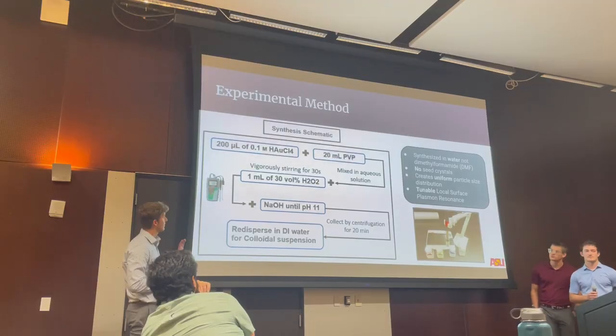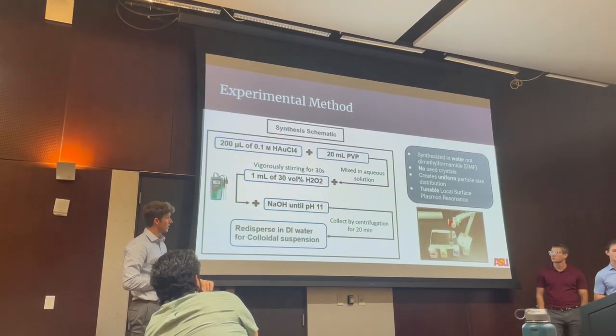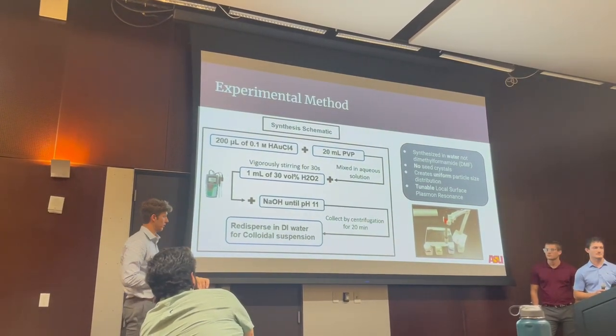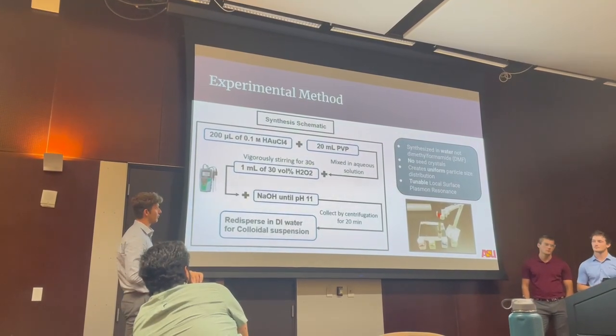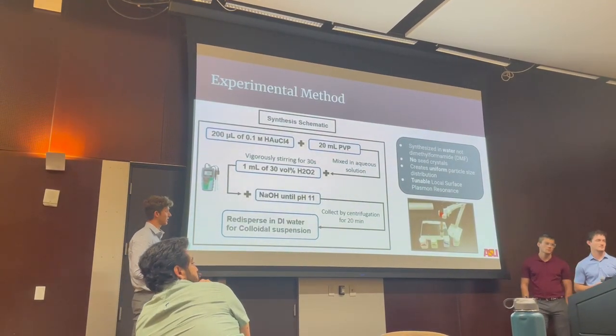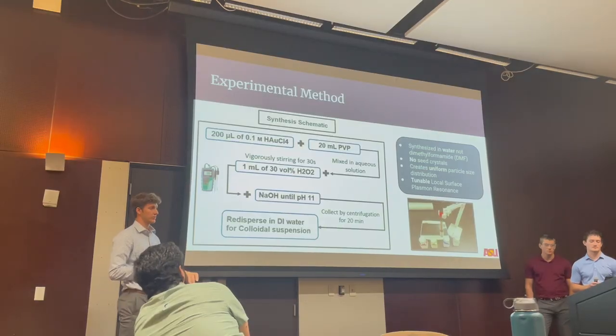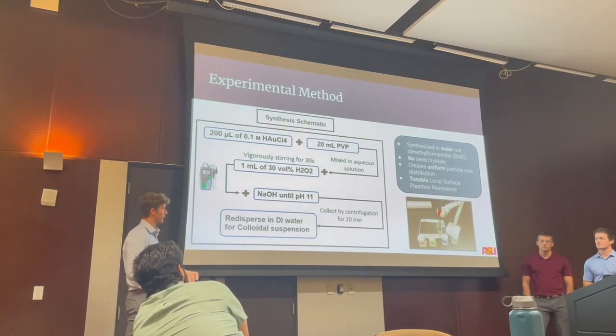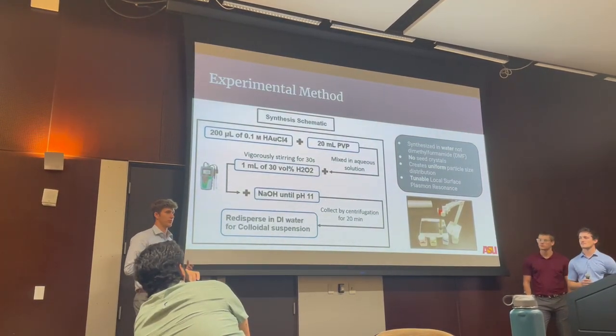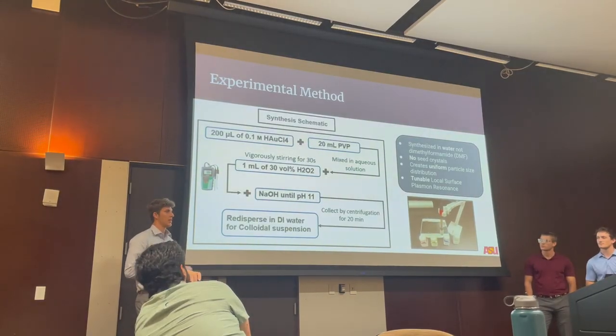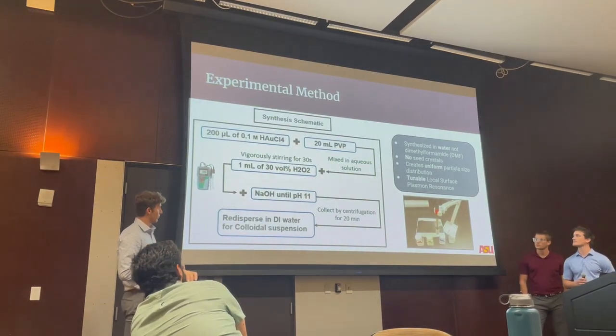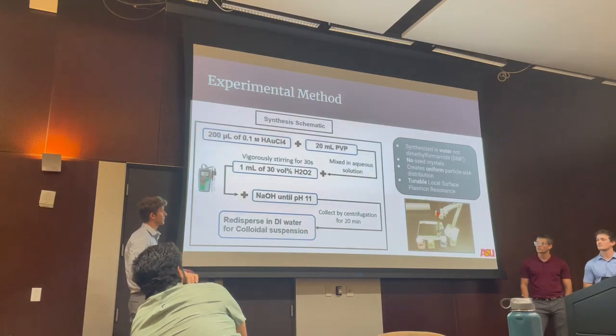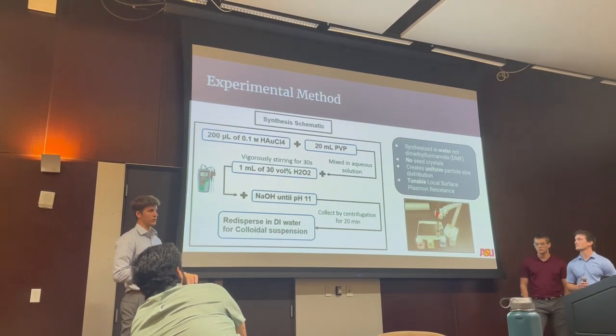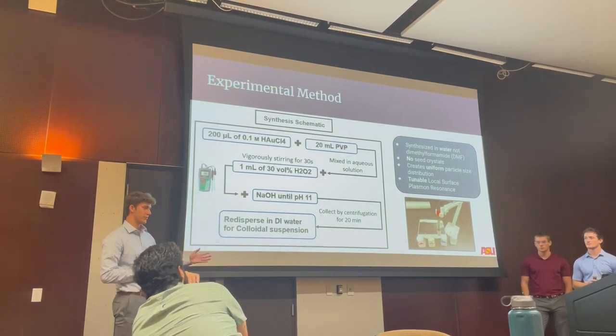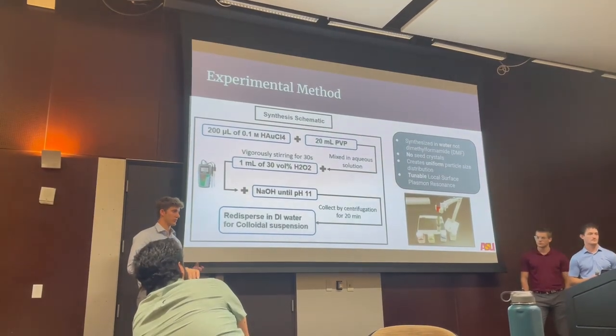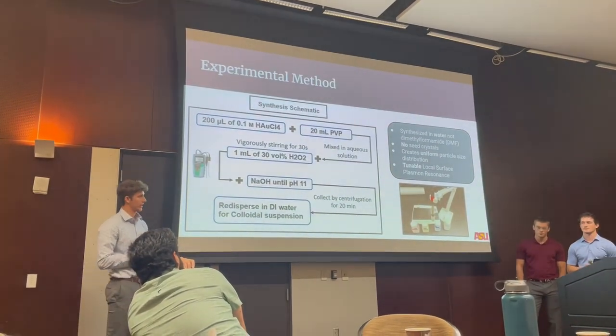So the important thing about this experimental method is that it's synthesized in water. A lot of methods we found in our literature review are synthesized in dimethylformamide, DMF, which is toxic to the body. It requires no seed crystals, making it a simpler procedure, and it creates uniform particle size distribution, which is important so that they all absorb the same NIR wavelength. And one of the big factors in this synthesis procedure is that it allows for tunable local surface plasmon resonance, which is that photothermal effect that Jack was talking about, which allows these particles to vibrate and heat up, killing the targeted cancer cells.